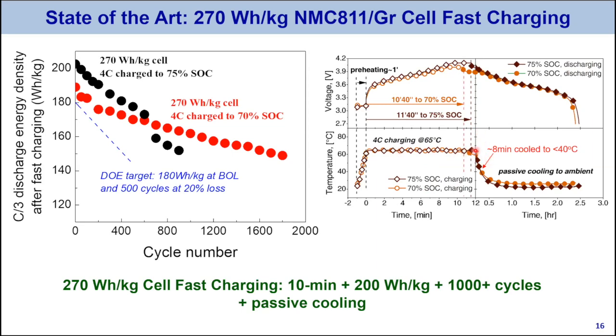And then after you fast charge, you will follow with C/3 discharge. This is mimicking a situation where we leave a fast charging station and then start to drive on the highway at the speed limit. In other words, consume the entire cruise range within 3 hours, right? And that's really the speed limit. Even if you do so, you see the cell temperature will drop very quickly to below 40 degrees Celsius in about 8 minutes in this case. It's all natural convection, nothing else, right? And below that, we know the cell is very safe.